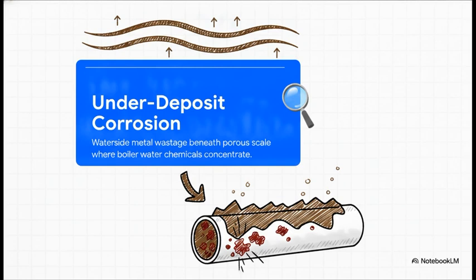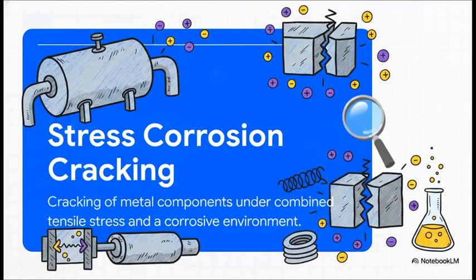Boiler water chemicals like sodium hydroxide seep into those pores and boil off. What they leave behind is a highly concentrated, incredibly corrosive puddle trapped directly against the metal. It just quietly rots the tube away, totally hidden beneath a layer of scale, until, boom, you have a catastrophic failure. And finally, we have stress corrosion cracking, or SCC.